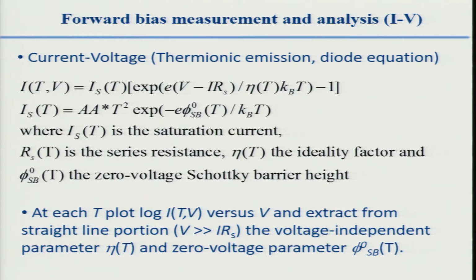And the saturation current is written in terms of some constants, A T squared, and the 0 voltage Schottky barrier height, which I'll describe how we measure. And R_S is temperature dependent, and so is this 0 voltage Schottky barrier height. Okay, so the way we analyze this is at each temperature you plot the log of the current versus voltage and extract from the straight line portion, for voltages larger than the voltage drop caused by the series resistance, the voltage independent parameter eta. So notice that this exponential for the voltages we use is always a lot bigger than 1. For positive voltages, if I reverse the voltage, this term is very small, and the -1 dominates. That's why you get the diode.